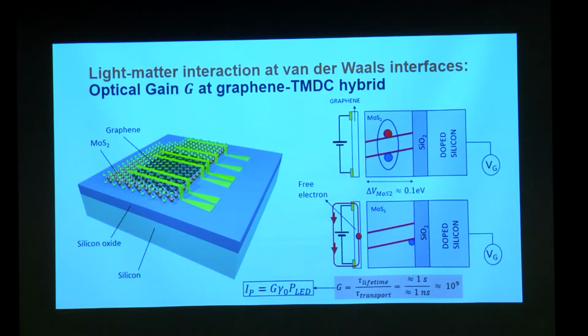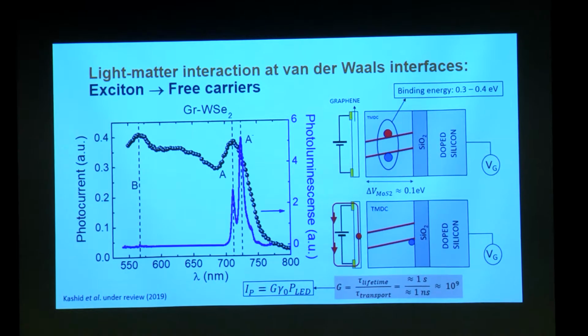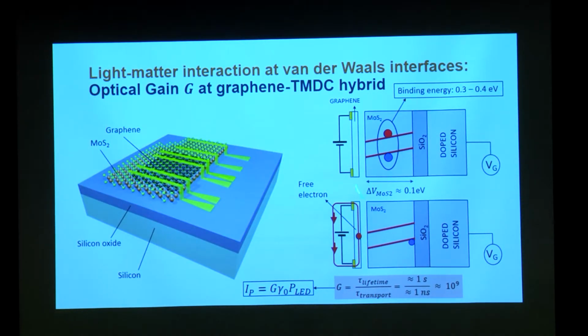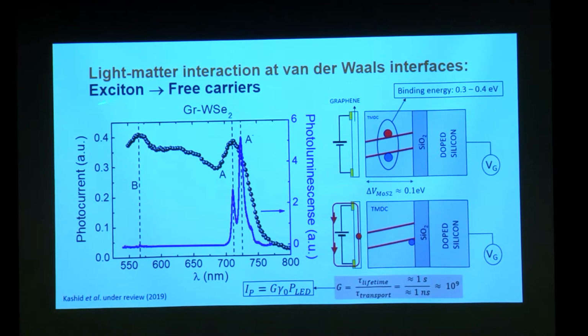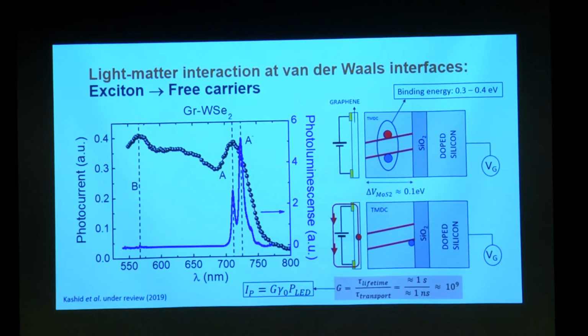But electricity comes because the electron is free, whereas in the case of an exciton, the electron forms a bound state with the hole inside the semiconductor. So the natural question to ask is, given that the binding energy of an exciton in the TMDC, the molybdenum disulfide layer, is 0.3 to 0.4 eV, how does an exciton lead to free carriers? The free carriers are obvious, because the whole process comes from the exciton. You can see we measured the photocurrent in graphene as a function of the wavelength of light that I illuminate on it, and wherever the optical density of states is higher, that's where the photocurrent started going up, becoming finite. Which means the origin of this photoconduction is dissociation of excitons in the molybdenum disulfide layer.